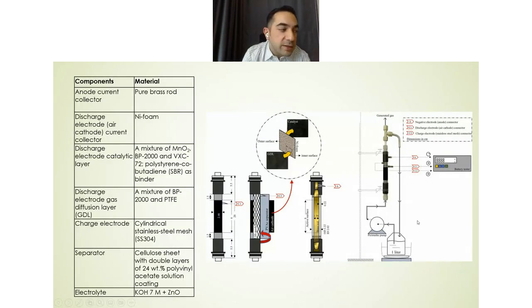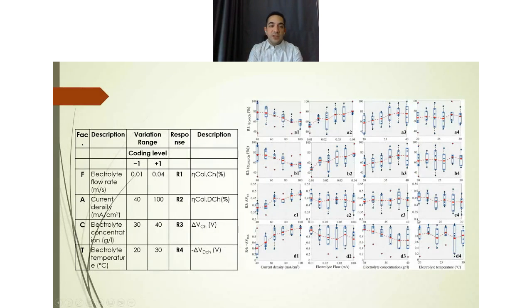To evaluate the optimization, the battery was charged and discharged while a different flow rate, current density, electrolyte concentration, and electrolyte temperature within the range that you can see in the table were applied. As a result, the Coulombic efficiency of charge, Coulombic efficiency of discharge, and also the overpotential of charge and the overpotential of discharge were measured.